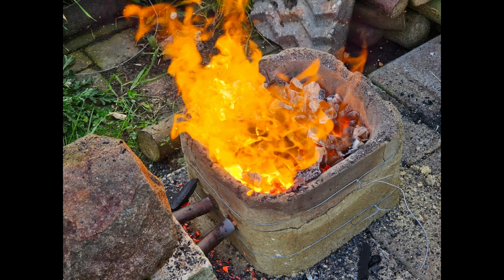On top of this, if wood ash was used as a flux during the hearth refinement technique, the calcium content of the hardwood ash has the ability to absorb phosphorus out of the liquid steel into a calcium phosphate rich slag, purifying the metal considerably.